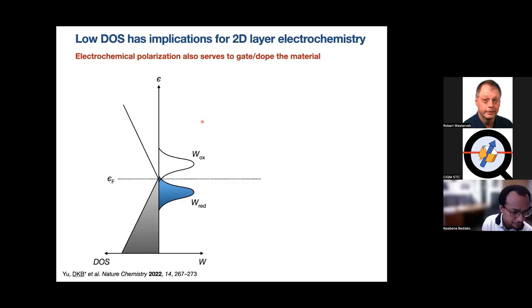And we spend a fair bit of time thinking about what is going on here, because it turns out that with quantum materials, when you're doing electrochemistry, and this could be nanotubes, all kinds of systems that people are using, like MoS2 for hydrogen evolution reactions and so on, it is really important, though not always considered, that the electrochemical polarization that you apply not only leads to a voltage drop across the electrochemical double layer, as I showed in one of the earlier slides, but it actually serves to gate or dope the material.